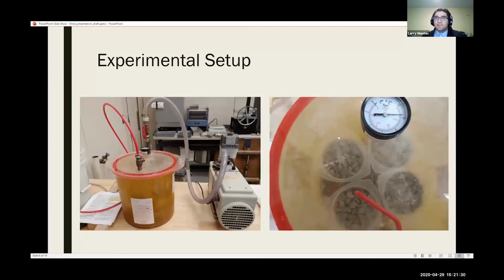And here are two images of the vacuum method. So here's the vacuum, and inside this chamber, which is vacuum sealed, on the left we have the 3/4 inch Norlite aggregate, and on the right we have the 3/8 inch Norlite aggregate. They would be inside this chamber for about 3 hours.